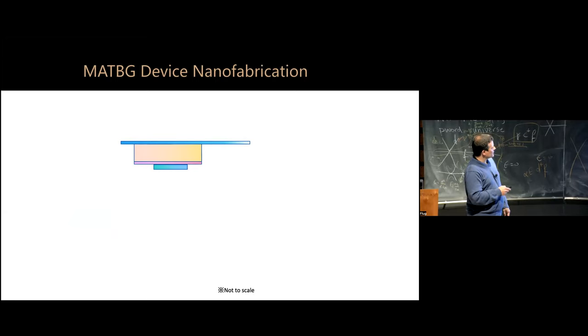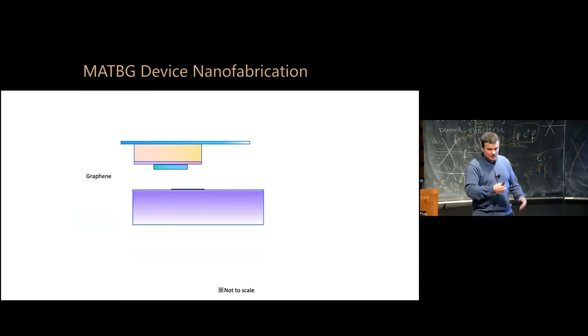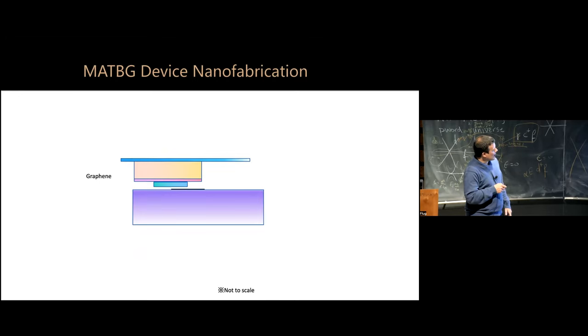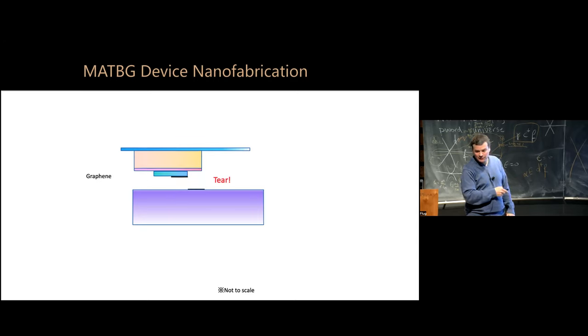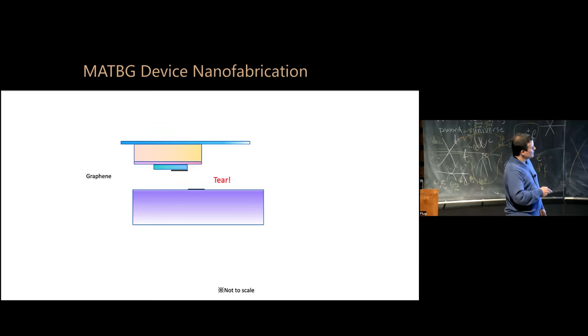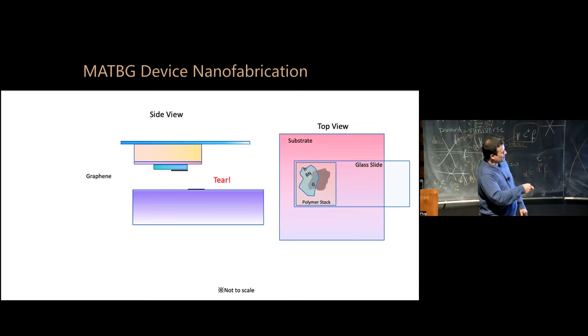Now we bring a different substrate with a graphene sheet on top, the same as the one that I showed you. Okay, silicon substrate with a graphene sheet. And we position very carefully this boron nitride. Halfway, the edge of the boron nitride is now halfway on top of the graphene. Okay. Go down, and the boron nitride is a little bit sticky to the graphene, so it picks up half of the graphene. Okay? On the top view, now I have my silicon substrate, I have my glass slide, I have the polymer, I have the boron nitride with half of the graphene. And I have the other half of the graphene down there.